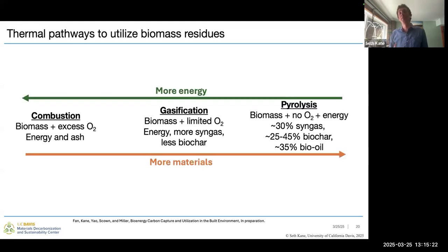And then our final method here is pyrolysis. That is the typical process that's used to produce biochar. And it will produce, in addition, about 30% of the weight of the original biomass as syngas, about 25 to 45% biochar, depending on the ash content present in the biomass to start with. So that ash is going to end up in the biochar along with that carbon product. And then in addition, a bio oil, which is a mix of lower molecular weight carbon products that are in the liquid form. You can run this process at different heating rates.